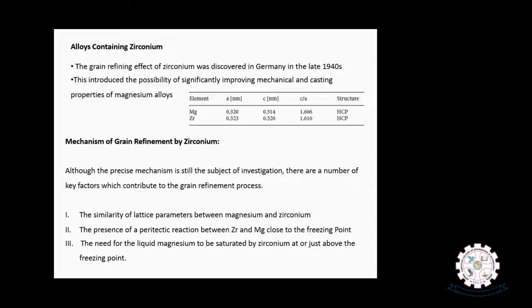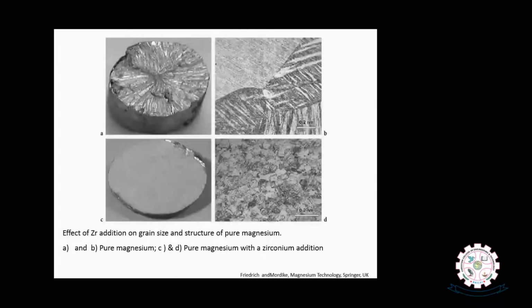So when we see the phase diagram of magnesium and zirconium, we understand that exactly at the freezing point, we find a peritectic reaction between the magnesium and zirconium. That might be the probable reason behind the grain refinement that we see when we add zirconium to magnesium. So this typical microstructure comparison will demonstrate the effect of zirconium addition on refining the microstructure of magnesium